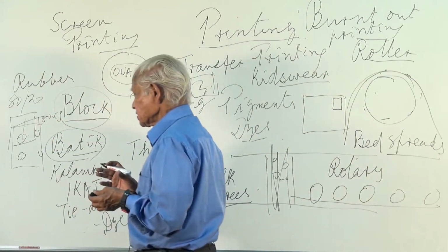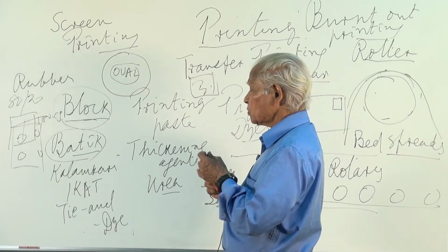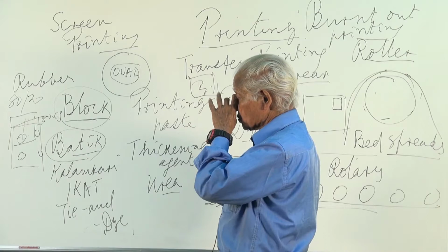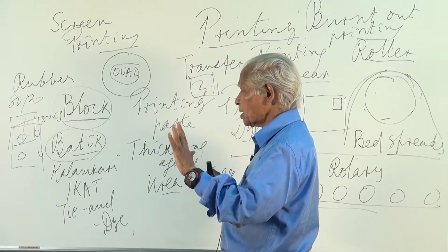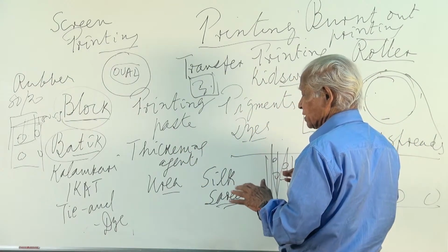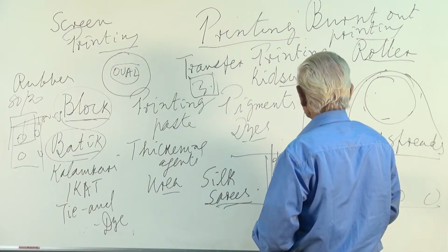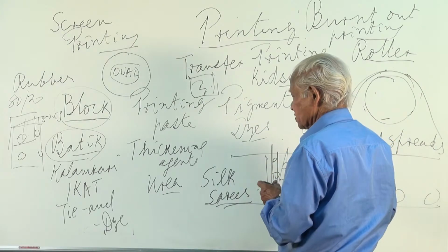In burnt out prints, it is very important that the warp and weft are intact even after burning out the other fibers. So 80% sulfuric acid is used. It should not cause a hole. Rather, a design is being produced on the fabric by making use of the solubility parameter of the cellulose using sulfuric acid. So that is the concept of these burnt out prints.